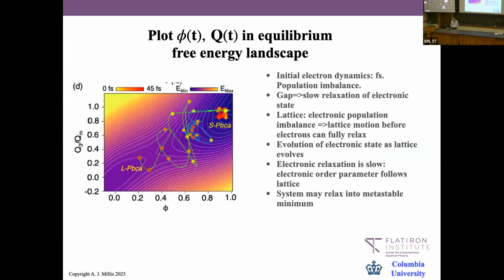And just one remark. You'll notice the way this works basically, and we're still trying to decide how much we believe it, it's a clear result of the calculation. What happens is we've changed the electrons. That makes a force on the lattice. The lattice goes down. In my belief, it has strange trajectories in here, but it's only when you get down to a place of relatively small lattice distortion, meaning relatively small electronic gap, that the electronic distribution can relax. So in this calculation, you decrease the order parameter a little bit each time you oscillate the lattice far enough down to reduce the gap to be small enough that you get some noticeable relaxation. That's what's going on in this calculation as far as we can tell.